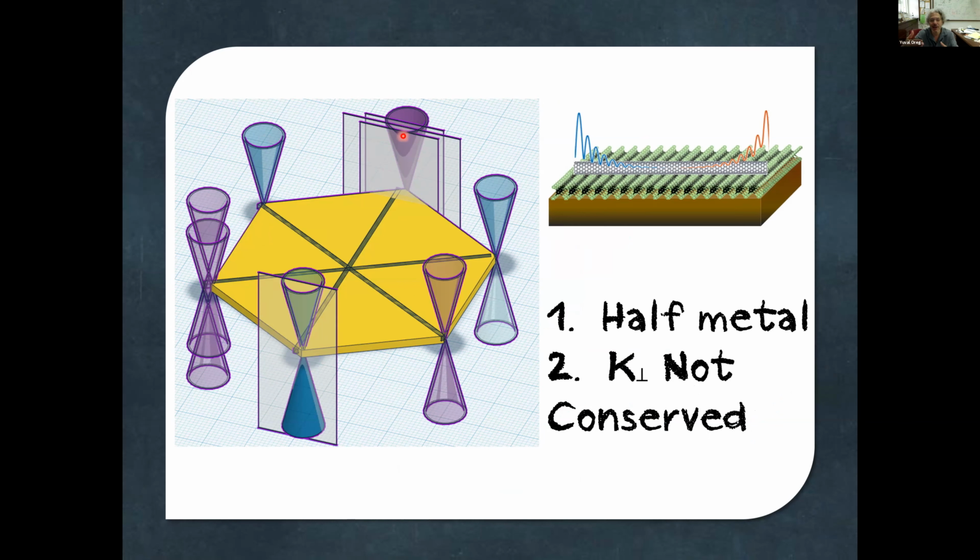You have something at the gamma point, something near the K prime point and the K. And the important thing is that there is a huge spin orbit coupling here, which separates spin up and spin down. You can appreciate that in figure D, where the scale is electron volt. The difference in the energy at this point between spin up and spin down is of the order of 0.1 electron volt.